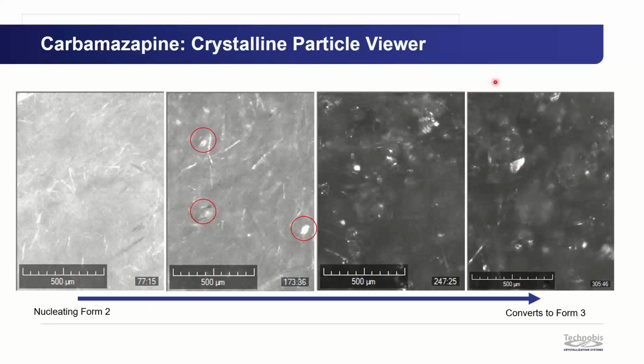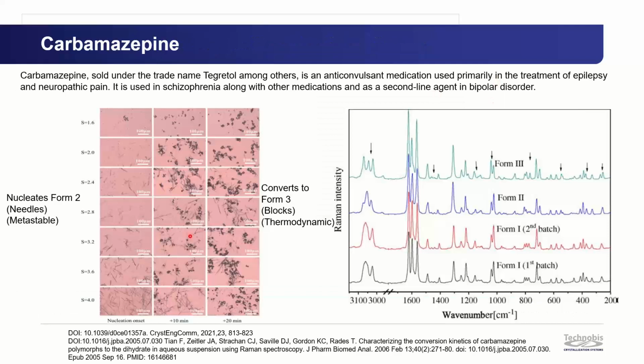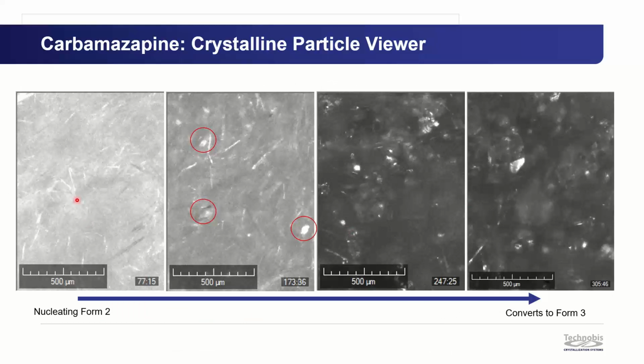So we decided to use the Crystal16 to generate a solubility curve, identify and calculate the solubility, the supersaturation and concentration needed to generate, say, 4.0 supersaturation, and then conducted a rapid cooling experiment, by dissolving form 3 and then crash cooling to generate supersaturation as fast as possible. And with this, we were able to nucleate form 2 with these needles. Over time, this gradually starts to convert to give us these blocks, which are quite faint. And then gradually the needles start to disappear more and more, and we get more and more blocks. And in the end, we just have large individual crystals of the form 3 converted.